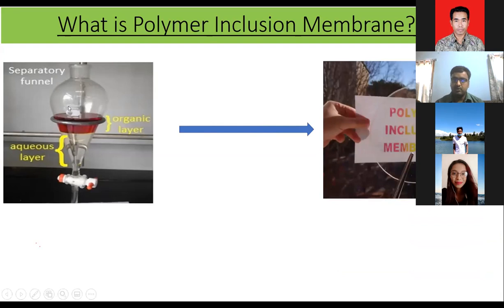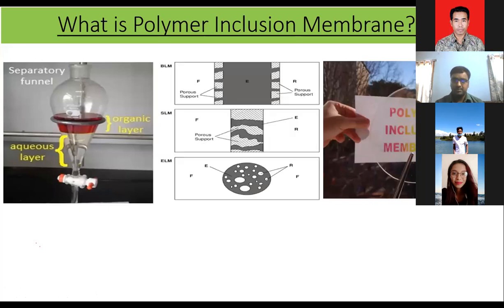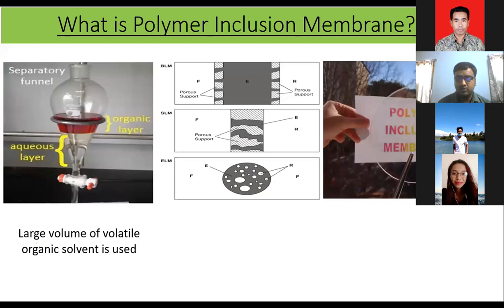In the organic layer, we have some organic solvent, but in this membrane we hold this extracting agent within the polymeric membrane using some base polymer. The transition from solvent extraction to polymer inclusion membrane also happens with a few other kinds of liquid membrane, which are called bulk liquid membrane, supported liquid membrane, or emulsion liquid membrane. The transition from solvent extraction to polymer inclusion membrane is always associated with some benefit, because when you are using solvent extraction, there is a use of a large volume of volatile organic solvent, and the organic solvent that we use is very toxic.